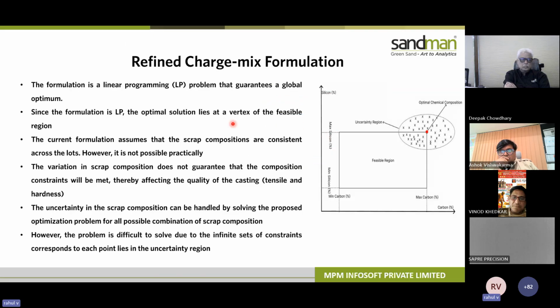So we found one drawback in this refined, typical formulation. What was that? This formulation was an LP. So this gives us the best possible solution, the least costly charge mix that can be produced under these constraints. But what if our scrap has an uncertainty? Let's take a pig iron with carbon percentage of 4.18. Its carbon percentage is not always 4.18. If I take each pig iron scrap and look at it, they won't all have the same 4.18 carbon percentage. Some might have 4.1, some might have 4.2, some might have 4.5, maybe. So this creates uncertainty in the charge mix.